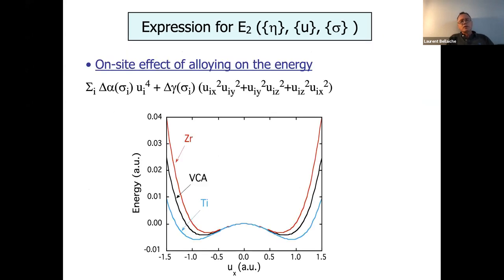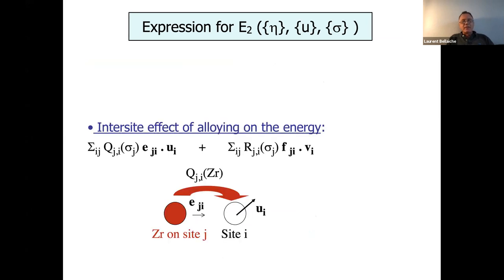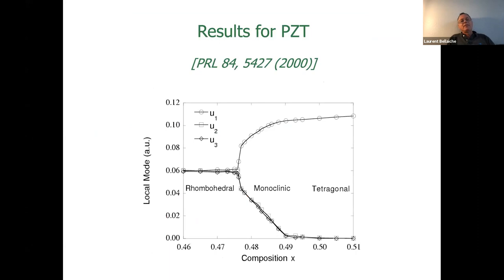So let me go through E2 because this was the novelty at that time. So you have two new energies. One characterizes the on-site effect of alloying on the energy and is basically telling you how zirconium or titanium ions are modifying the double well potential with respect to the virtual crystal alloy. The second kind of energy is an intersite effect. Imagine I have a zirconium on site J. How is it going to modify the local dipoles on site I close to it, or the strain around it? So quite easy. And then these are the results.